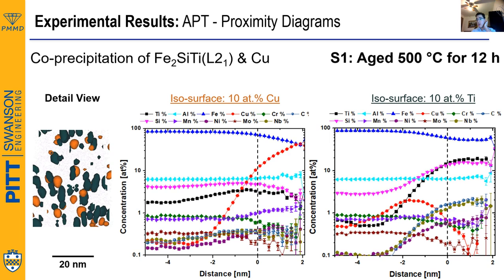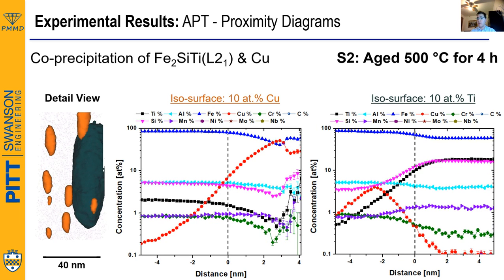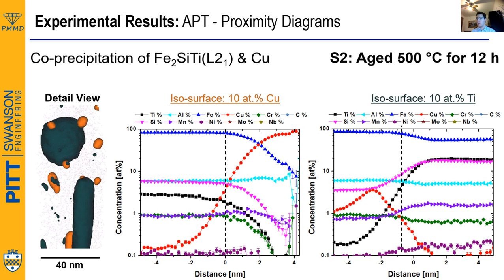in the case of S1. For completeness, we also have the proximity diagrams of S2 aged at 4 hours and 12 hours, and we see a very similar behavior. Even in this case, it's more clear precisely because of the bigger size of the precipitate. Finally, here's the 12 hours aged S2, and again, we see how the copper content increases in the vicinity of the interface between the ferrite and the L21 phase.